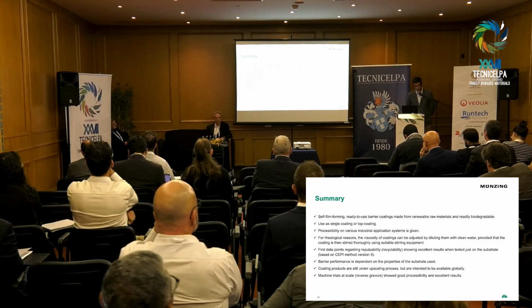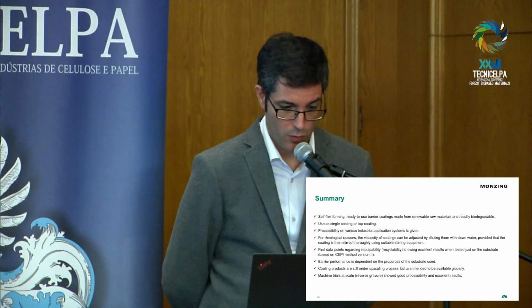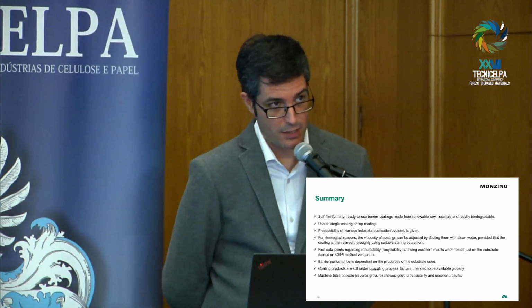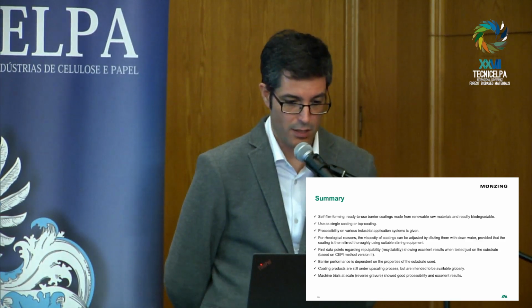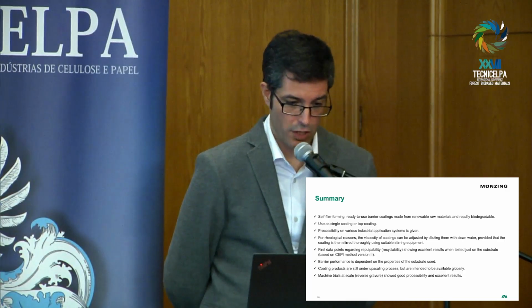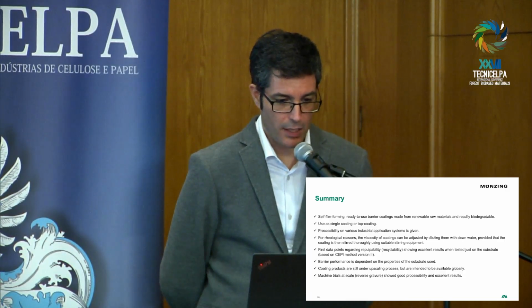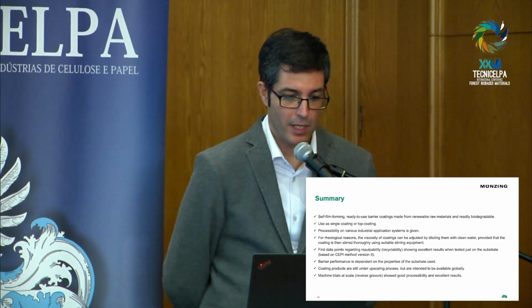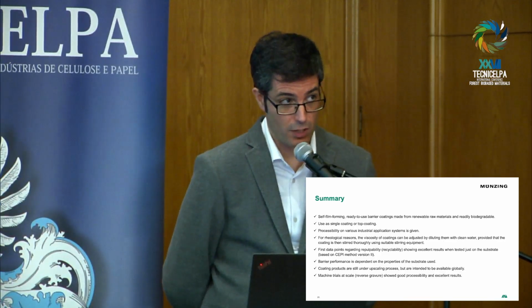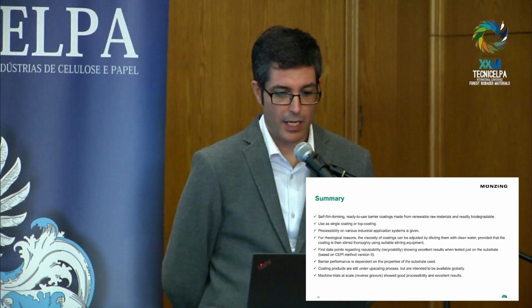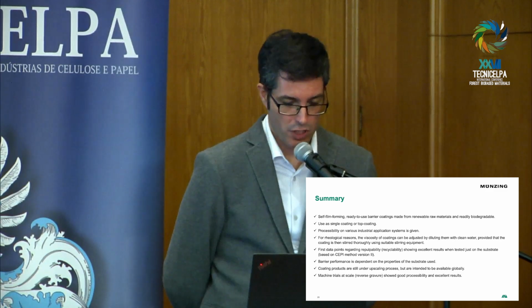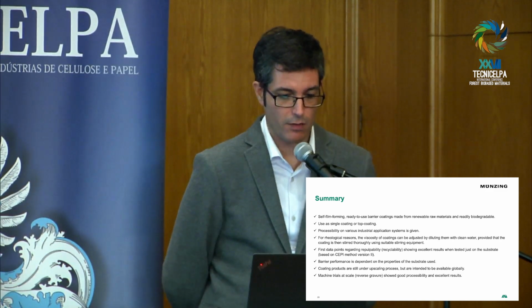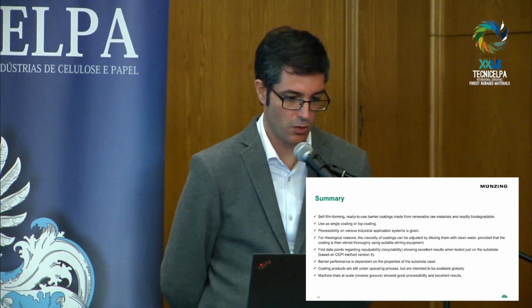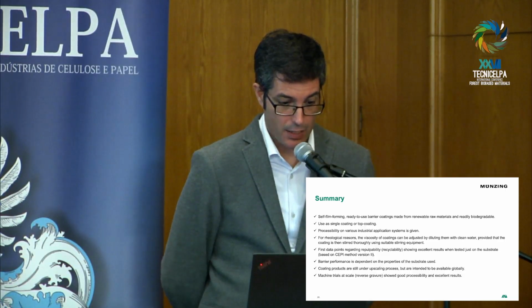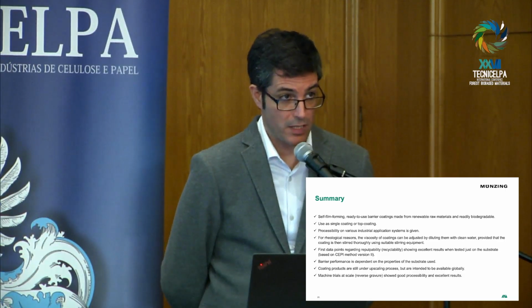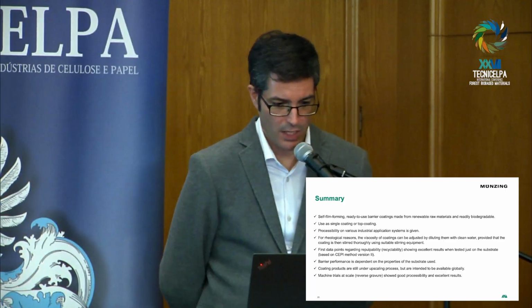It is possible to adjust the material for rheological purposes. When the material is too thick, it can be adjusted with water, always controlling that it is stirred properly before using. Those products cannot prove repulpability on their own because it also depends on the complete system. But regarding some projects we did with some customers, we prove that all of them are, so it's also good news. Also, it has been proved that the barrier performance depends on the substrate as expected.